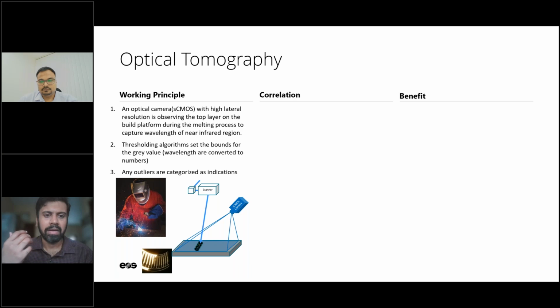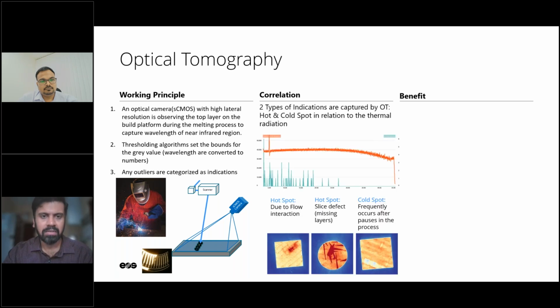Right. So the sCMOS camera captures these reflected radiations, which are very close to the wavelength of the laser, and then sees whether this matches within the threshold set by the user. Right? Any outliers for this threshold are captured as an indication. So there are two kinds of indications that come in. One is called hotspot, the other is called cold spot. And for each hotspot, the user will say, okay, this hotspot could be a reason for so and so defect.